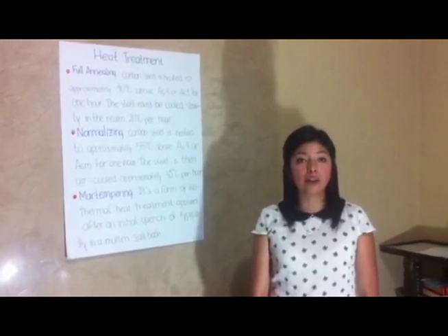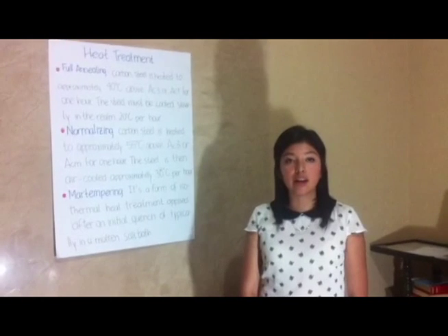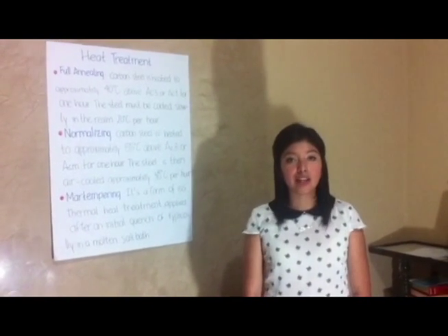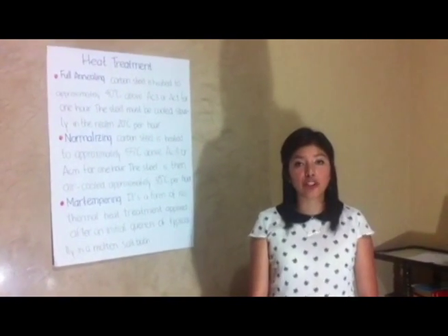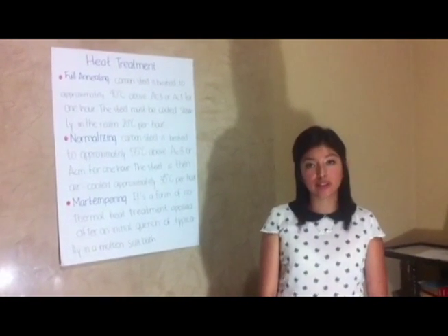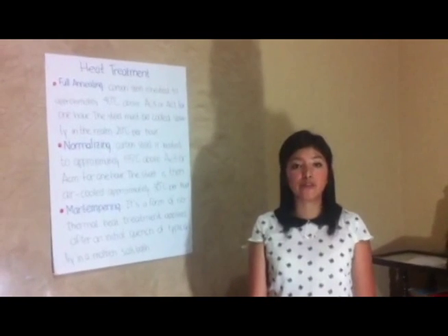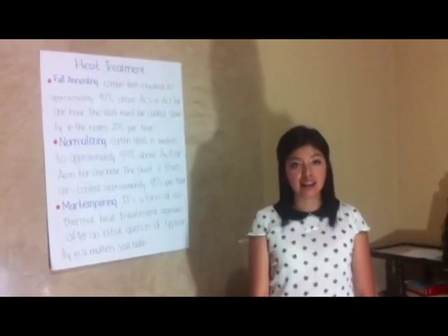The steel must be cooled slowly, around 20 degrees per hour. Usually, it is just furnace cooled, where the furnace is turned off with the steel inside.